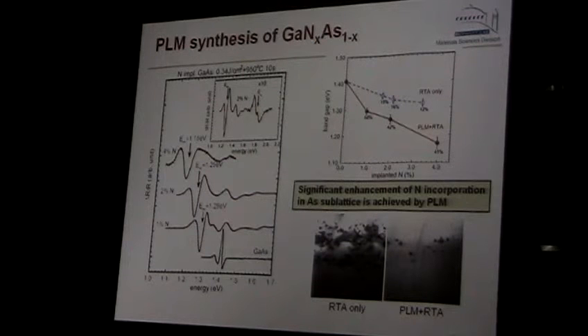So some of them escape or form bubbles, but the quality of the material finally after some annealing is pretty good. So this is the material, this is the substrate, and this is our layer on the top. There are some defects here, this black spot. So this is a very promising method to synthesize material.